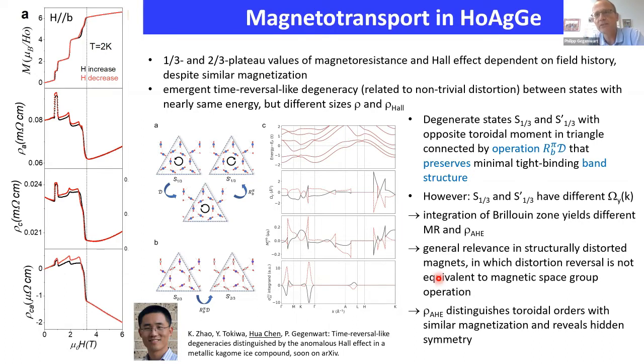And Hua Chen helped us to understand this phenomenon, and actually he found that this is related to the non-trivial distortion of the Kagome lattice, which we have in our material Ho-Ag-Ge. Because there are these two different states, which, while they feature the same magnetization and energy, give rise to different Berry curvature and thus different magnetotransport properties. These two configurations are actually related by a non-trivial operation, which includes a distortion reversal, as indicated here, where the individual triangular units change their distortion, and then a rotation by pi along the b-axis.